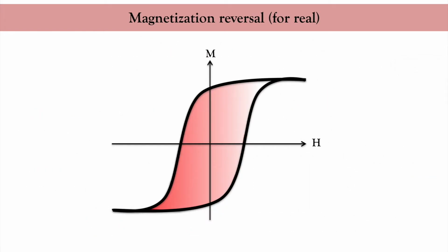To finish this discussion, let's go back to the hysteresis that we first discussed in the context of Stoner-Wohlfarth Model. As we have seen, many complex processes contribute to the magnetization reversal in realistic samples. Thermally activated Stoner-Wohlfarth model consistently apply to small magnetic systems with large anisotropy. In larger samples though, even if the external field is aligned along the z-axis, there's little chance I'm going to observe square hysteresis. I rather observe a rounded hysteresis like that.